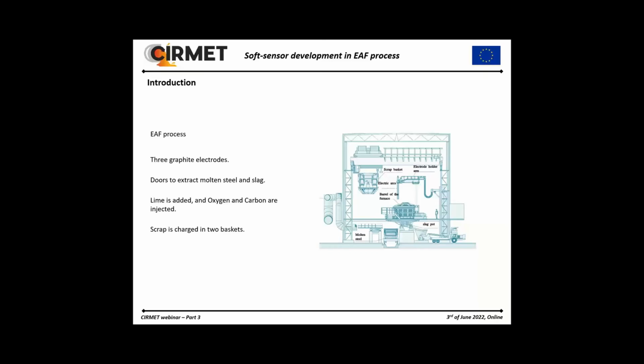The scrap is inserted into enormous baskets, and part of the additives, such as the lime, are added in each basket, and the rest is added in the last stage together with the injection of oxygen, carbon, or gas. The generated slag quantity forecasting is one of the most critical process parameters and should be under control. The slag is extracted from the furnace using a slag pot to be measured, and after every casting the generated slag is removed from the furnace using that slag pot. Nevertheless, there is always some quantity remaining in the furnace.